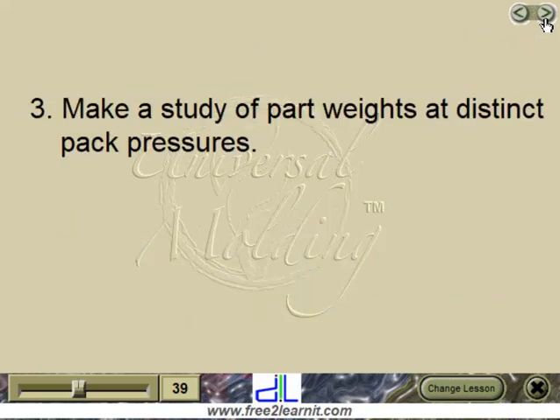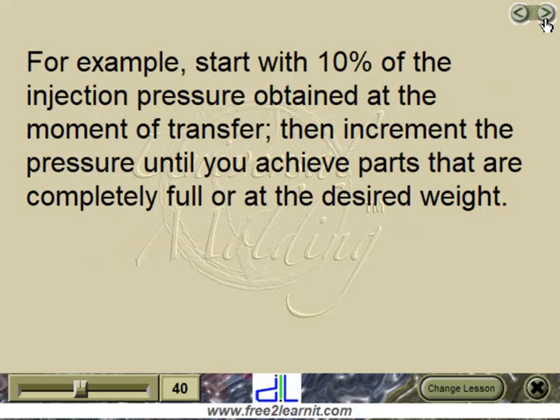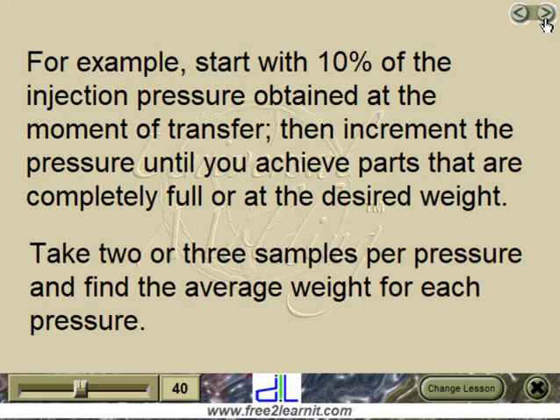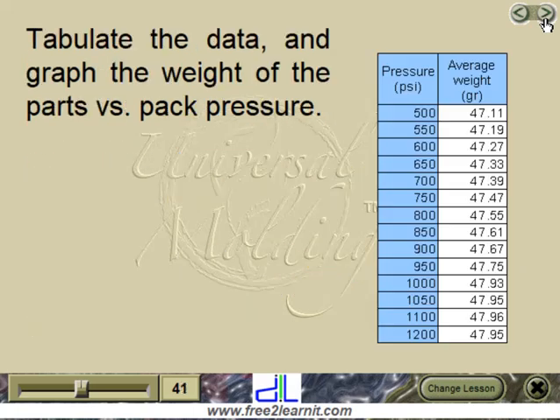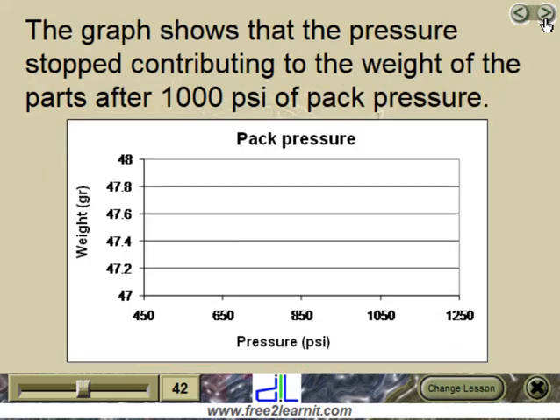Step 3: make a study of part weights at distinct pack pressures. Begin this experiment with a pressure that is less than required — for example, start with 10% of the injection pressure obtained at the moment of transfer. Then increment the pressure until you achieve parts that are completely full or at the desired weight. Take two or three samples per pressure and find the average weight for each pressure.